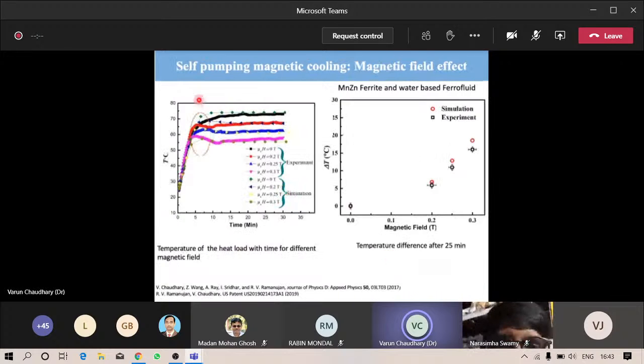For self-pumping magnetic cooling, we see the effect of the magnetic field here. The black curve here shows the case without magnetic field. And then we apply 0.2 Tesla, 0.25 Tesla, and 0.3 Tesla. For this study, the maximum field we applied was only up to 0.3 Tesla. And then, yes, we found that with increasing field, the cooling increased.